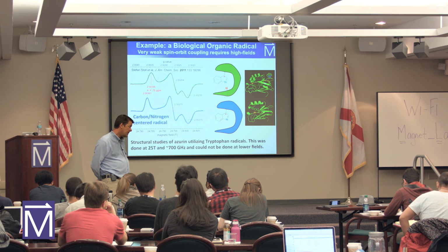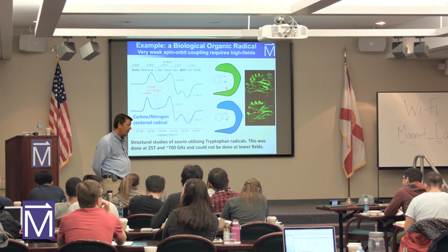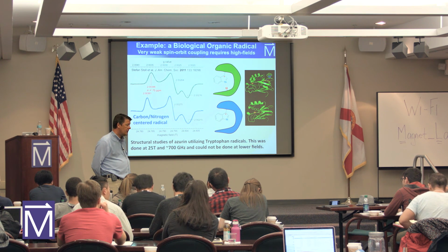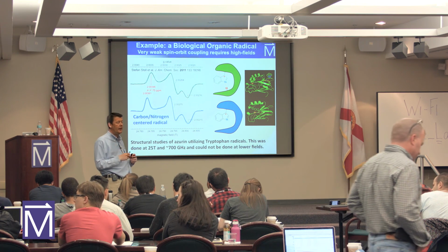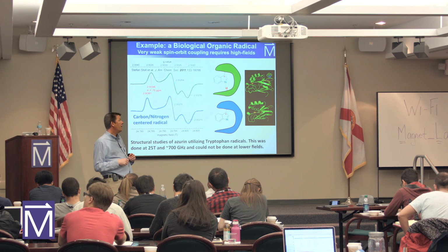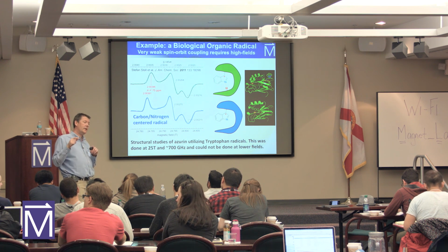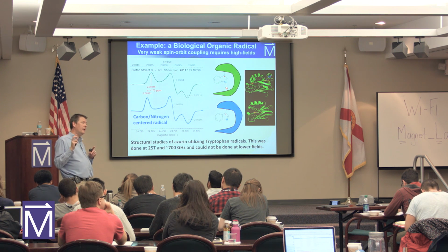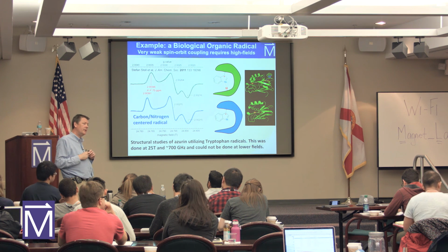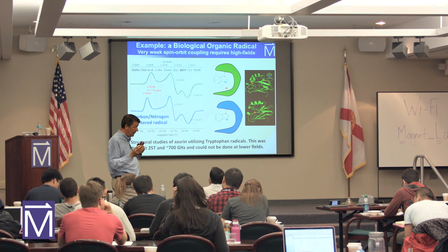Yeah, it's a very good question, because EMR and neutrons are obviously highly complementary techniques. Neutrons have some disadvantages: you often need large samples, you need stuff which doesn't have a lot of protons, and good large single crystals. There are certainly cases where you can gain the same information from EMR. You have to be a little careful, because the selection rules for EPR are different from the selection rules for neutrons. So neutrons measure some things better than electron EMR does. However, there are definitely cases where we can measure these anisotropic terms in EMR. I'd have to know the specific case more directly.